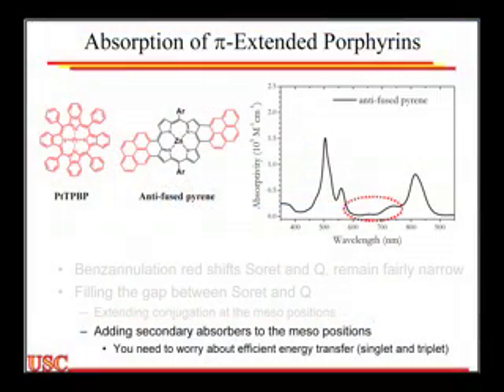And so if I compare the tetrabenzoporphyrin to this fused bispyrenyl porphyrin, I get two benefits. One of them is I get a redshift, which I wanted, and I also get a significant increase in line width for both the Soret band and the Q band, as I shift from the tetrabenzo to the bispyrenyl derivative. But the big problem is in both cases, I'm left with an open space. That is, if I'm sticking with a porphyrin, I'm always going to have a dead zone between the Soret and Q bands. There's nothing here. The absorbance is quite low. Even though the absorbance at the peaks of the Q and Soret are high, the absorbance here is really low.